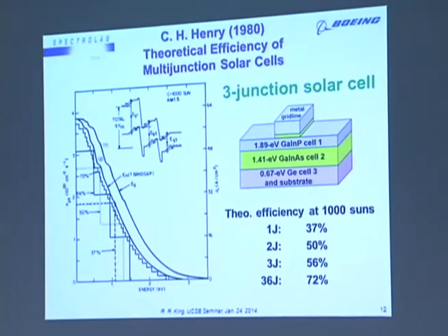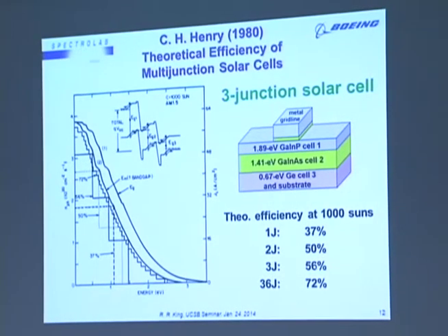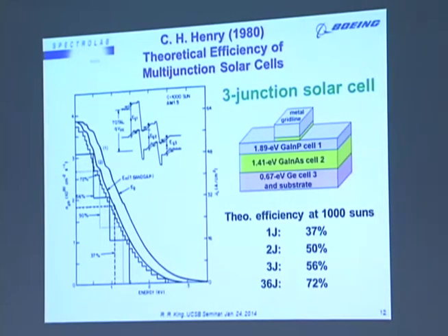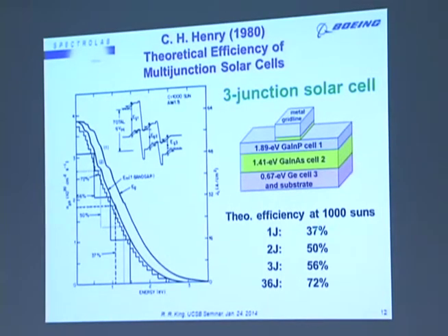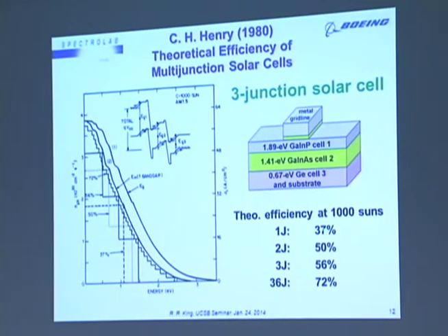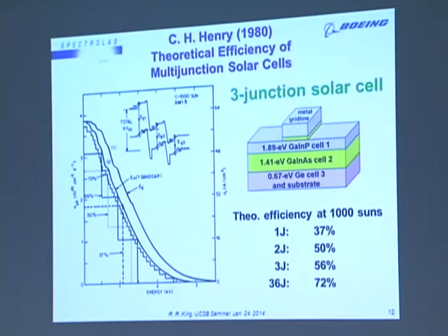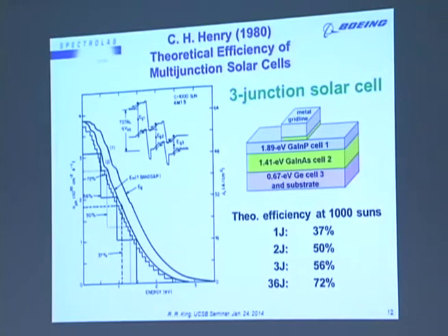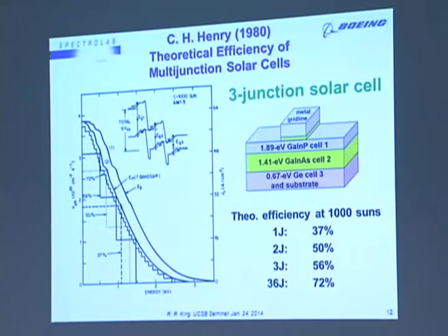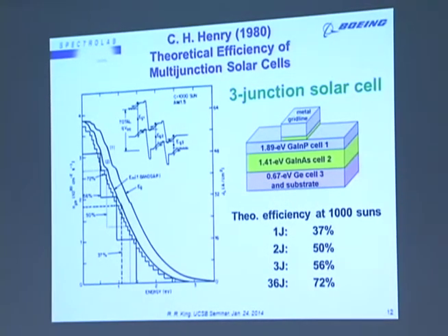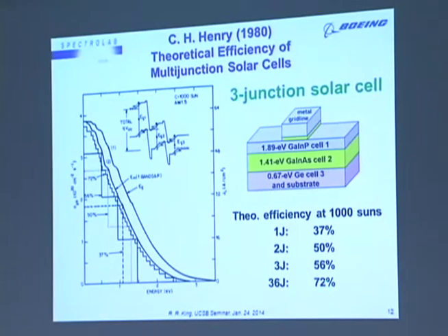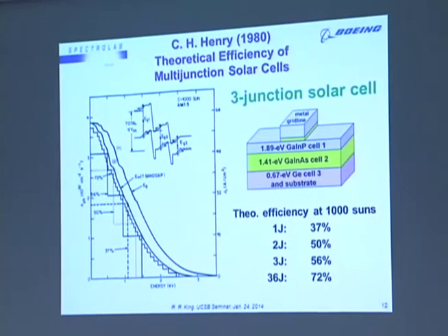So the theoretical efficiency of a 3-junction cell, for instance, is now up to 56%. And you can see the advantages of going from a 1-sun concentrator cell. The concentration brings that one single junction efficiency up to 37% instead of 30% at 1-sun. Adding another junction brings us up to 50%. 3 junctions brings the theoretical efficiency up to 56%. And having an arbitrarily large number of junctions, Henry modeled the case with 36 junctions, which is getting close to infinity in this case, of 72% efficiency modeled.